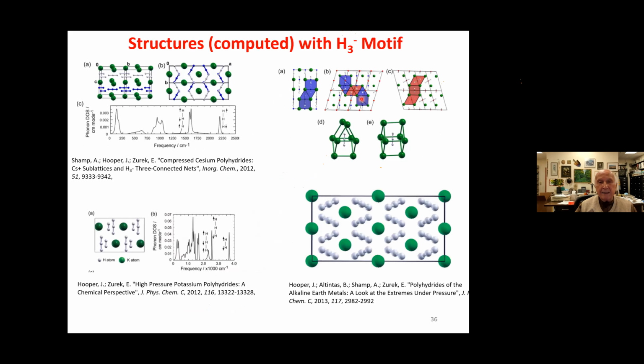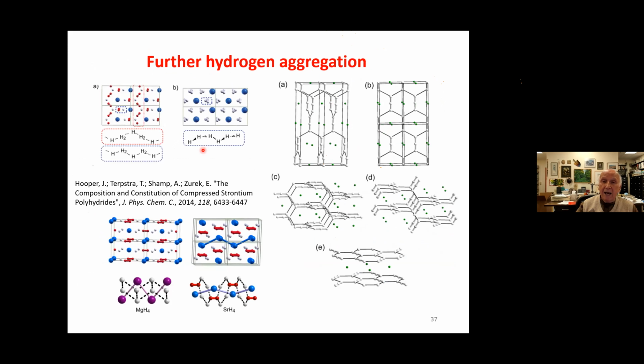In the solid state, Zurek's group has found a variety of structures with H3s. You can see them. They have even calculated the normal modes of vibration, the various phonon modes that correspond to a symmetric or an asymmetric stretch of these. The H3 minuses are definitely there in the extended structures. And as you get more hydrogen, you get further aggregation.